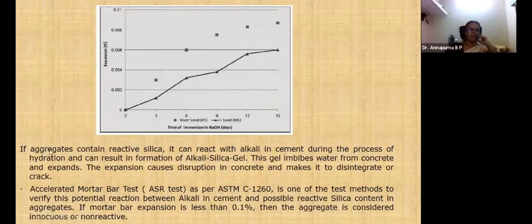If aggregates contain reactive silica, it can react with alkali in cement during the process of hydration and can result in formation of alkali silica gel. This gel imbibes water from concrete and expands. So the expansion causes disruption in concrete and makes it disintegrate or crack. So next is the accelerated test.